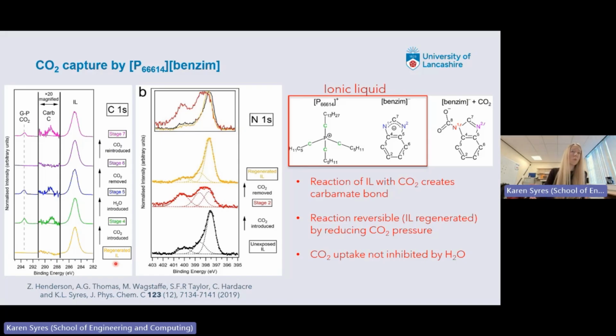We also did some measurements where we introduced water as well, and we found that the CO2 uptake didn't seem to be inhibited by the water in this case. It seemed to uptake the same amount of CO2.